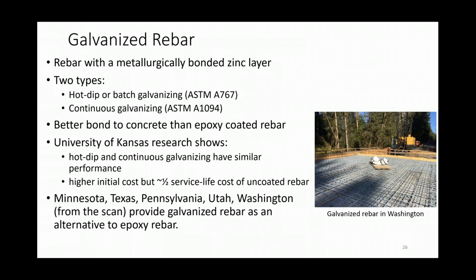So the bars get bent and galvanized at the same facility. So if you're close to this facility, it may be a good option to go for. They do not have the issue that epoxy coated rebar has with bonding to concrete. So it's essentially similar bond to concrete as you would have with your black bars.